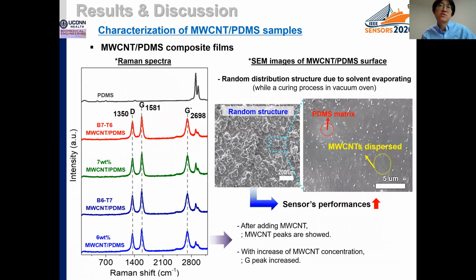To investigate the structure of the composite materials, we performed Raman spectral analysis. From the Raman data, we found that a new peak related to CNT appeared after adding MWCNT into PDMS, which means that the MWCNT were dispersed into the PDMS material. Also, we found that when increasing MWCNT concentration, the G peak indicating the MWCNT increases.